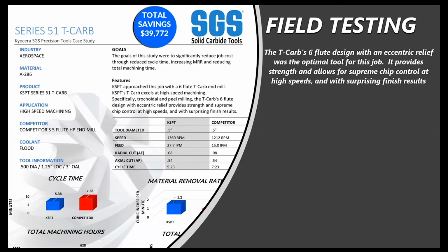Tool cost for the SGS tool in this case was slightly less, but we did increase the chip load from 0.0018 to 0.0034 inch per tooth. That equates to going from 15 to almost 28 inches a minute. SGS won this test based on the reduction of cycle time, and in the end, we saved the customer almost $40,000.